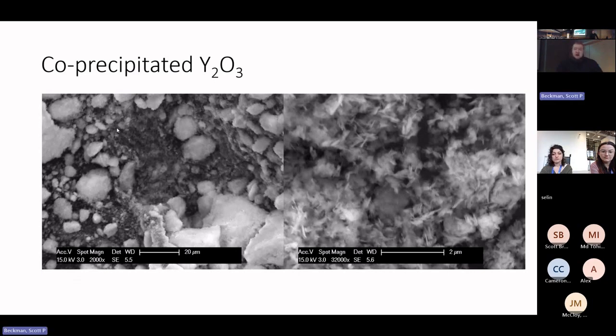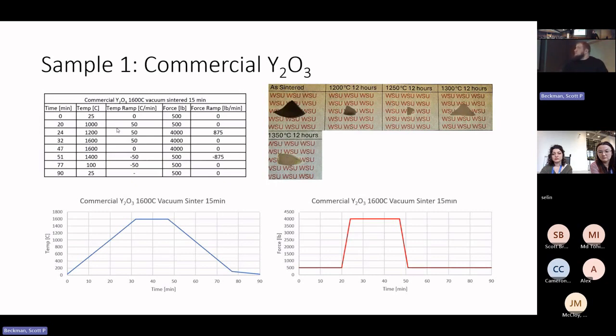But it is important to notice that the two powders we used in our experiments were very different and had very different outcomes. The first set of pellets that we produced used this commercial powder that we have, this more macro scale powder. And these are the conditions that we use to sinter our pellets.